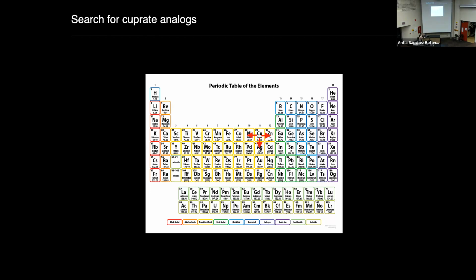And if you go back to the periodic table and you locate copper in it, you may start to think that there are a few things that you could try and do. You could go right and go to zinc, but zinc 2+ is non-magnetic. That's probably not a very good starting point. You could go down and go to silver, but in oxides, silver actually wants to be a valence skipper due to the difference in crystal field. It likes to be 1+ or 3+, but not 2+. So again, probably not a good starting point.